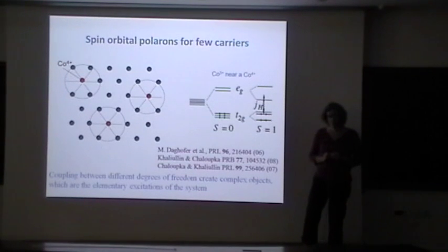Such a thing has been seen by neutrons for perovskite cobaltates. There are other types of cobaltates where, well, it's known that you can have these high spin states. Cobalt 4 plus creates rather big magnetic polarons, with six or seven cobalt 3 plus around it becoming magnetic, forming a total polaron.